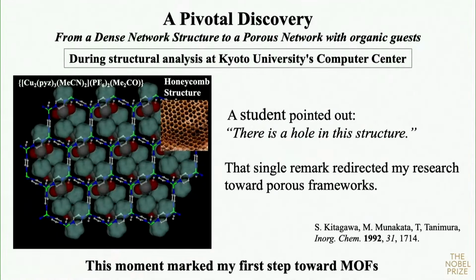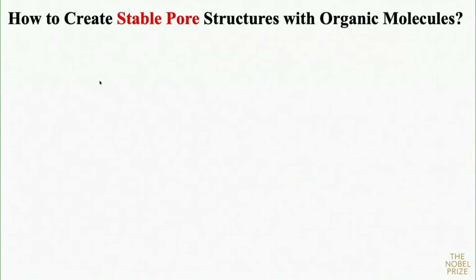However, one day I tried to determine the crystal structure with my students at the Kyoto University Computer Center. The center was so crowded. I had to wait for a long time, one or two hours, to analyze this data. In that time, we just analyzed the intermediate structure. The student said, there is a hole in this structure. I was so impressed and excited to see that in the cavities there is an ion and also organic molecules. So this moment marked my first step toward MOF.